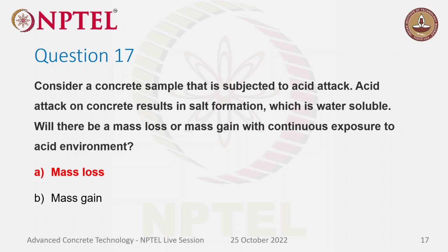If the salt is not water soluble, then what will happen? There will be mass gain initially. After some time, since there will be expansion due to the additional acid products formed, there will be expansion and cracking. Then the cracking will affect the hydrates inside. Finally there will be some mass loss due to destruction of the concrete structure. But normally, if it's a water soluble salt due to acid attack, then there will be mass loss. And if it's a water insoluble one, usually there will be mass gain only.